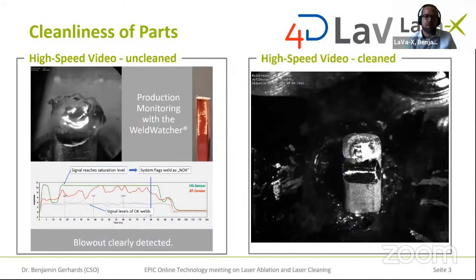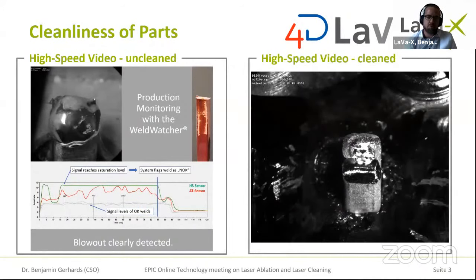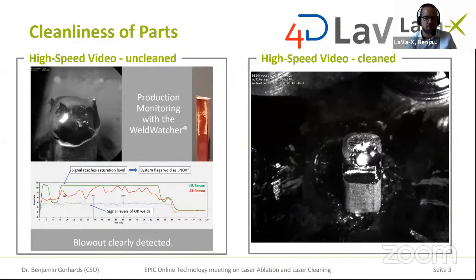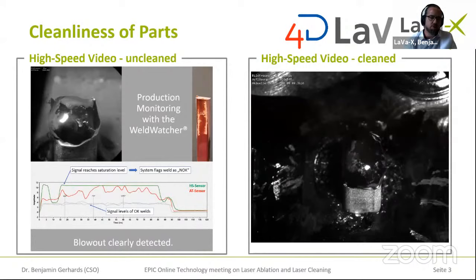If I may draw your attention to this, those pins were prepared by cleanLASER, and therefore you can see we have very, very low amounts of remaining material on the surfaces. And in combination with our very stable process, we do not get any spatter. So short circuits are not an issue here. And also we do not see any pores that occur.